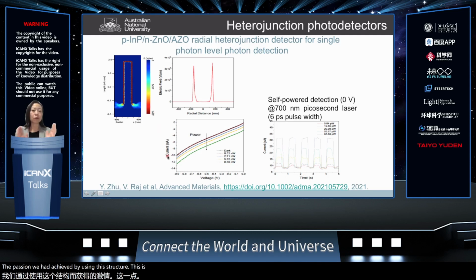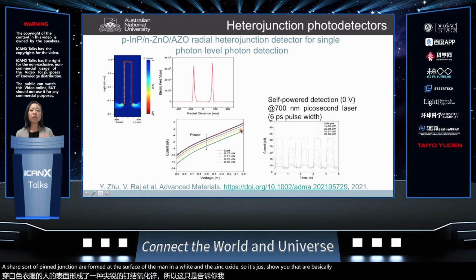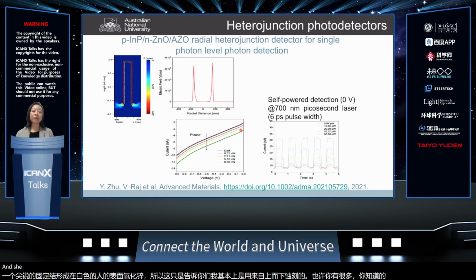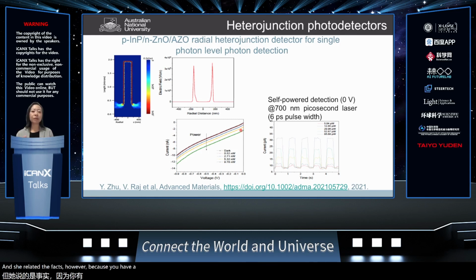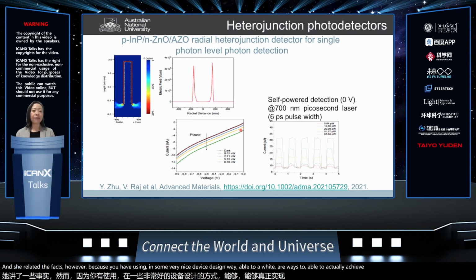This is just because of this very nice sharp PN junction formed at the surface of the nanowire and the zinc oxide. So it's just to show you that if you use top-down etching, maybe you have a lot of etching related defects. However, because you use some really nice device design, we're still able to achieve very high efficiency devices by using this technique.